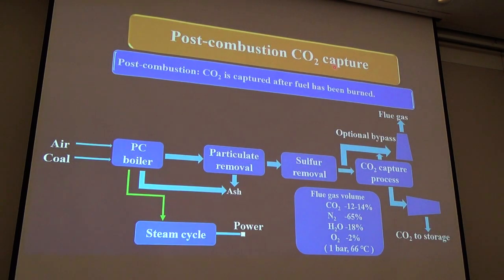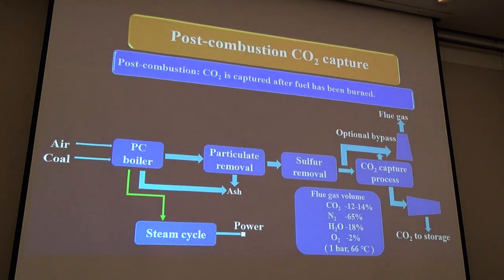Post-combustion CO2 capture is used for adsorption of CO2 from flue gas. Flue gas consists of 12 to 14% of carbon dioxide, 65% of nitrogen, 18% of water vapors, and 2% of oxygen. After burning the fuel, the stream gas is treated for particulate matter removal, followed by sulfur dioxide removal. Then the CO2 is captured from the stream gas, and this CO2 capture process is carried out at 1 bar and 66 degrees centigrade.